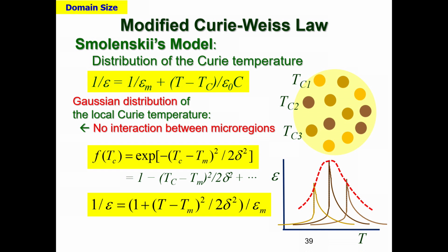So before moving into the fractal or the Curie-Weiss law or critical exponent, I'd like to introduce a modified Curie-Weiss law presented by Smolensky. Okay? Usual Curie-Weiss law, any person knows this. Like PMN, magnesium and niobium, the ratio is slightly fluctuating depending on each local position. If you consider this fluctuation of the compositions, he put the assumption that the Curie-Weiss temperature is changing around here. So the Curie temperature distribution is here to here, around here. Therefore, he supposed the Gaussian distribution of the Curie temperature. Accordingly, he derived the 1 over epsilon and temperature square relation, not just directly the temperature proportion, okay?